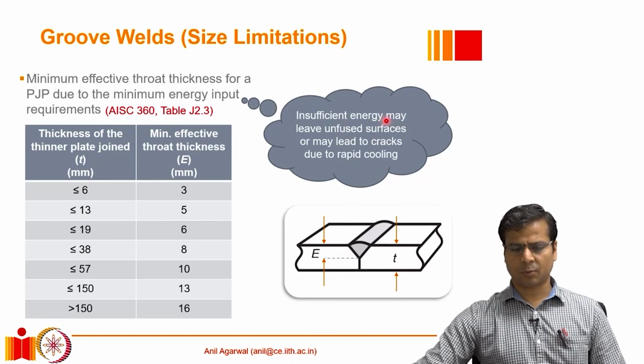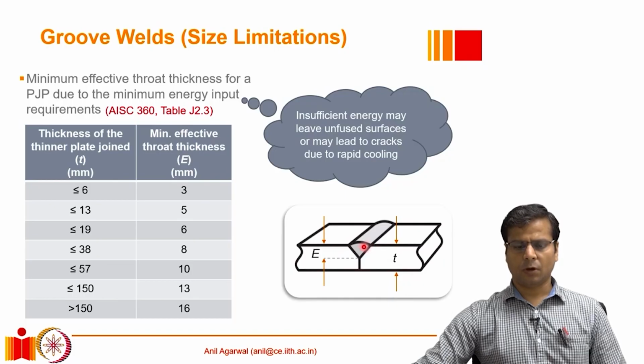If sufficient heat is not provided, one problem could be that the two materials don't fuse together. Also, another problem could be that the thicker plates cool down very fast. So if the heat is not sufficient, even after complete fusion, the heat will dissipate very quickly away from here, which will lead to large thermal stresses getting developed in the welded region. So it is better that the weld cools down slowly, and for that to happen, there has to be sufficient heat imparted at the time of welding for a given plate thickness.